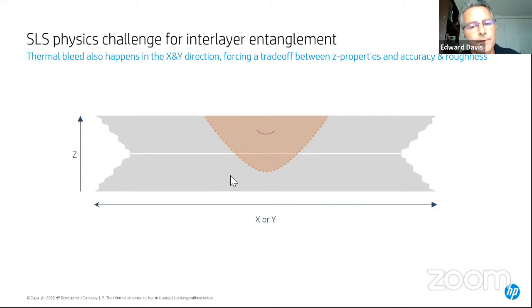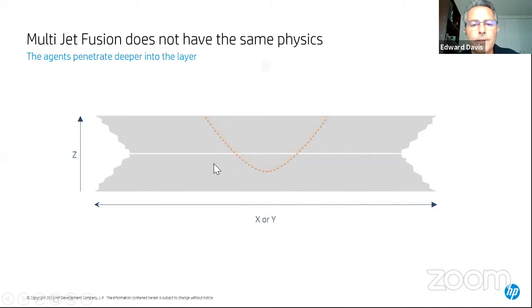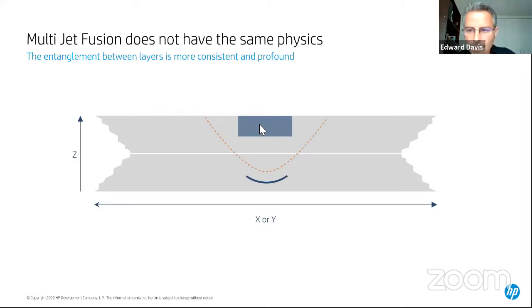So multi-jet fusion is very similar. We lay down a layer of powder, we melt. We lay down another layer of material, we melt. And what we do, in fact, is we put down a fusing agent. And the fusing agent, to be honest, only penetrates somewhere between 30 and 50 microns into that layer. And then we apply energy. And then, of course, we depend on thermal conductivity in the Z direction to get good melting as well, right? And we get better melting and better penetration in the Z.